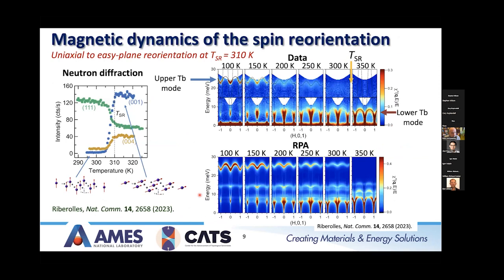All right, so I might start going a little quicker here. We looked at the spin reorientation transition to see what happens as we heat up. If you look at the top right here at 100 Kelvin, you see this upper terbium mode, again centered around 25 meV in this case. As you heat up, you start seeing the development of a mode down in with the manganese mode here, and that corresponds to this lower terbium mode that starts coming in. So you see the disappearance of the upper one, and this lower one coming in. They both coexist over a certain temperature range, and then once you get to the spin reorientation transition, the coexistence disappears and you're just left with this lower terbium mode.